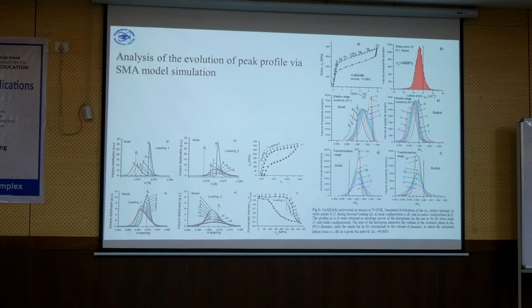Basically, from broadening, then it's becoming narrow. Usually it's called crystalline kind of behavior. But normally the peak broadening is related to the dislocation density. So this is what is known in the field. If you have a material which deforms plastically, in the beginning the peak is narrow and then it becomes broad. This is the state-of-the-art knowledge.